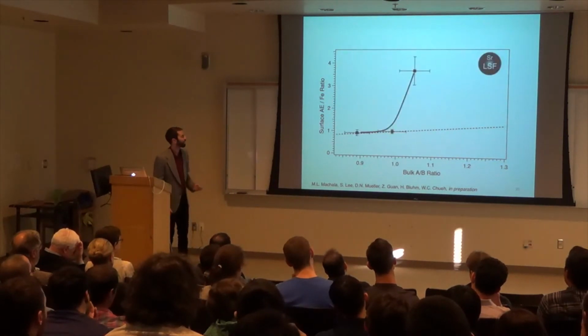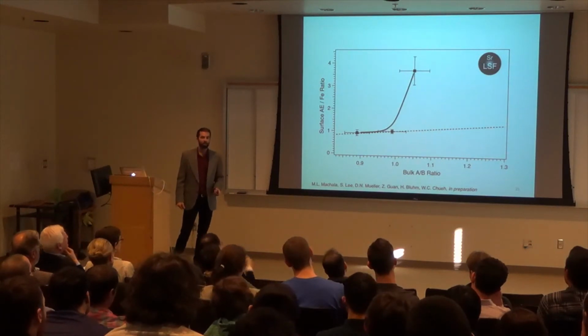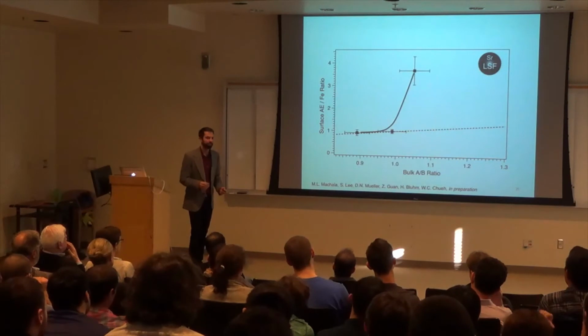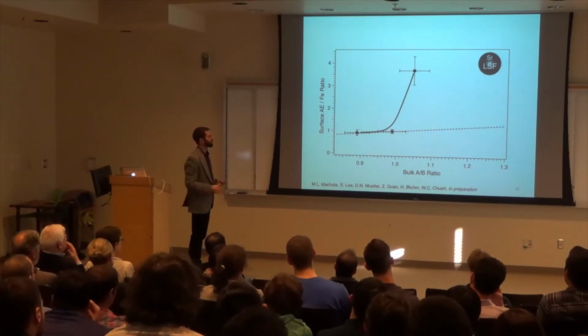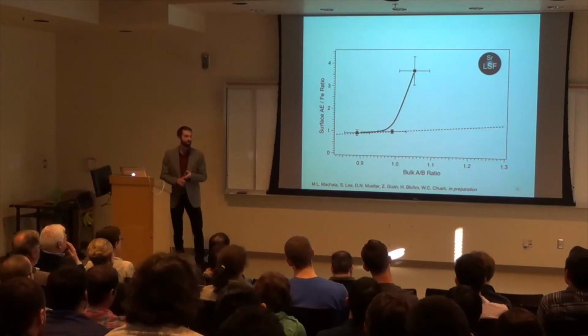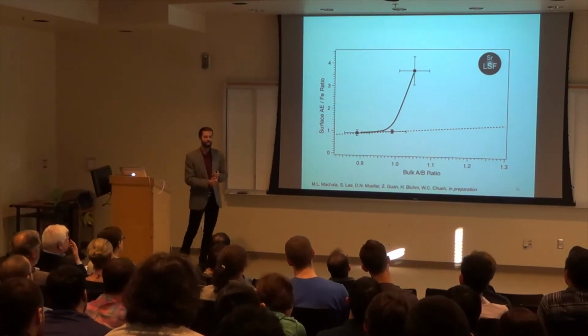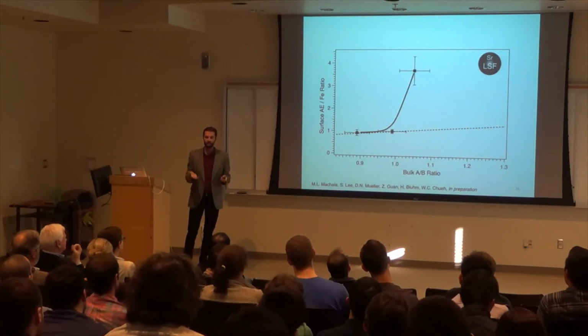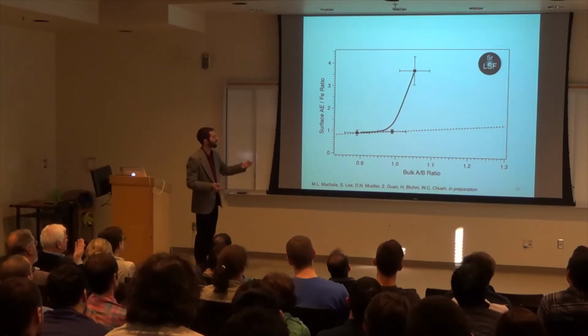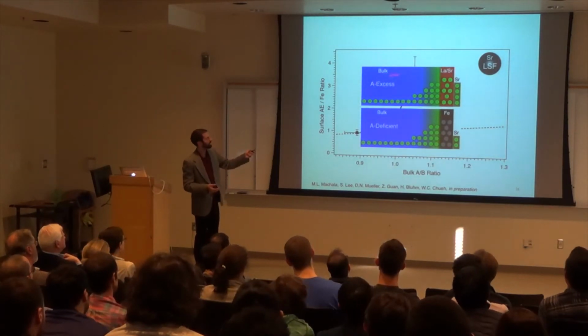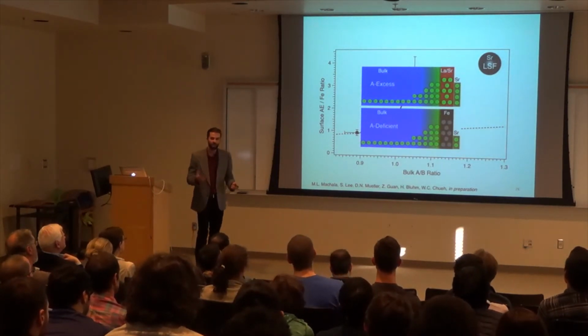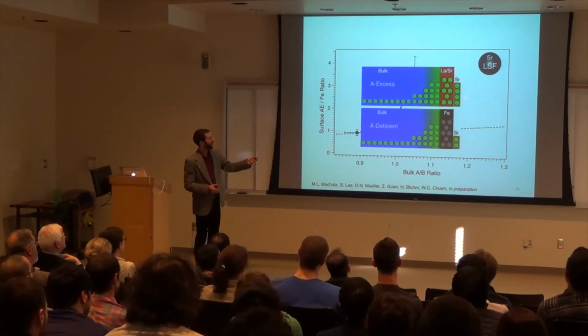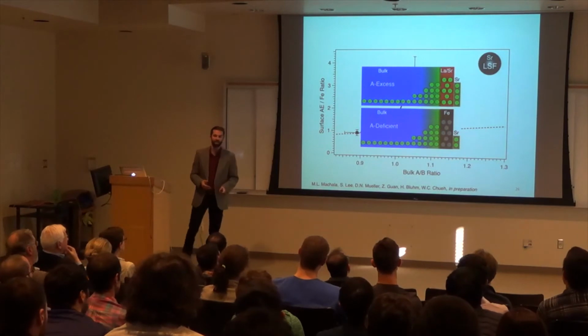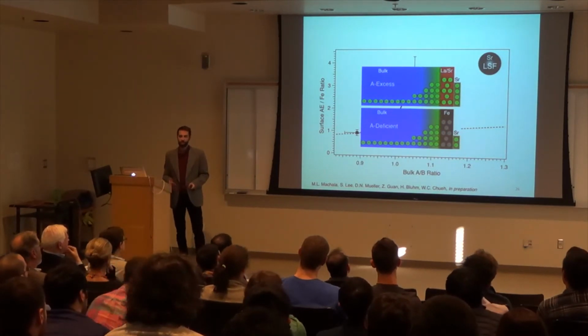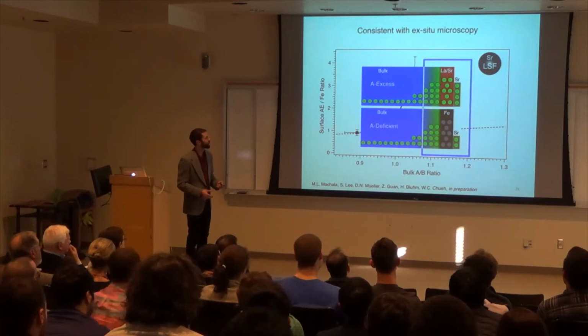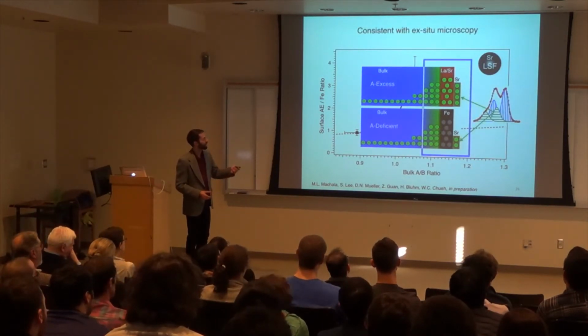When we compare the ratios to each other, we get this significant deviation. Now remember the picture that I showed you earlier with the electron microscopy, where we saw something change at the surface too. If we take into account the lanthanum, the strontium, and the iron spectra, we can actually reconstruct what these surfaces look like. And this is what we came up with. For the A side excess, we see an A side enrichment, just like we did in the microscopy. And on the A side deficient, we also see a B side termination, just like in the microscopy results. Further, we can actually resolve what we saw earlier for the side peak.